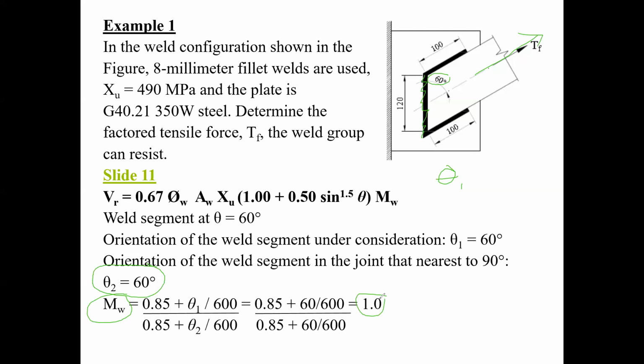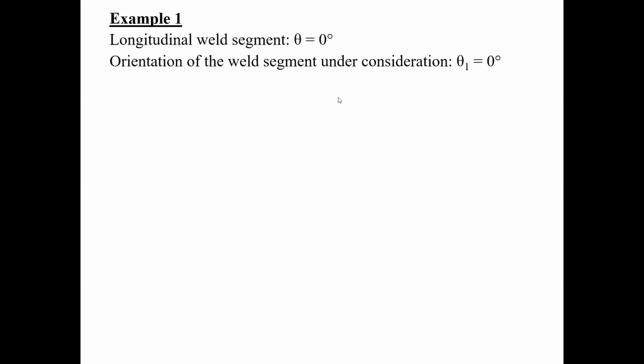I did this purely for academic reasons because this value here is the same as that value there, and therefore the Mw only for this weld segment here is equal to 1.0. So that's just for that one weld segment. Now, once I've got all that, I've got everything I need in here to be able to do this calculation. So now for the weld segment where theta is equal to 0, in other words, the ones that are horizontal, parallel to the line of action.